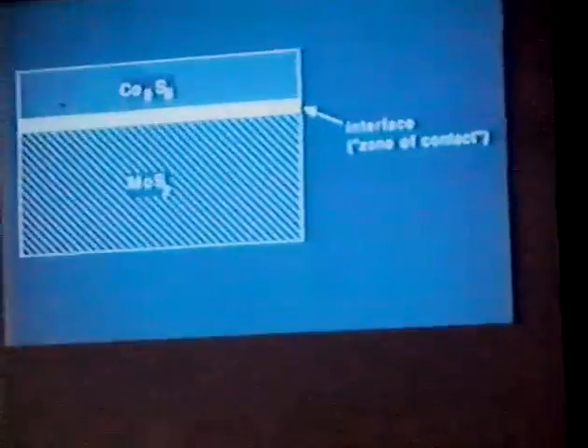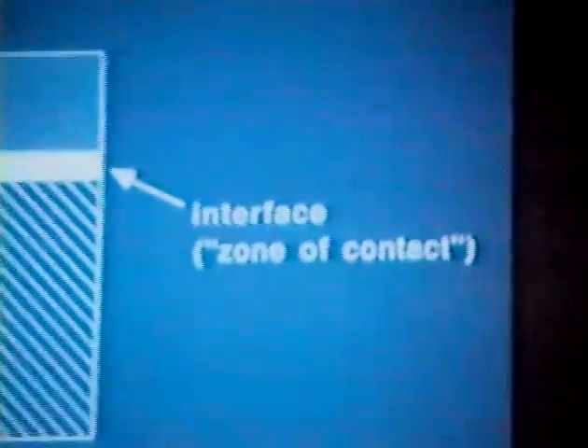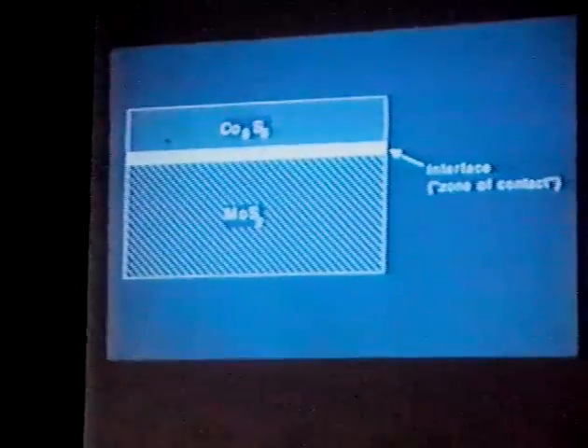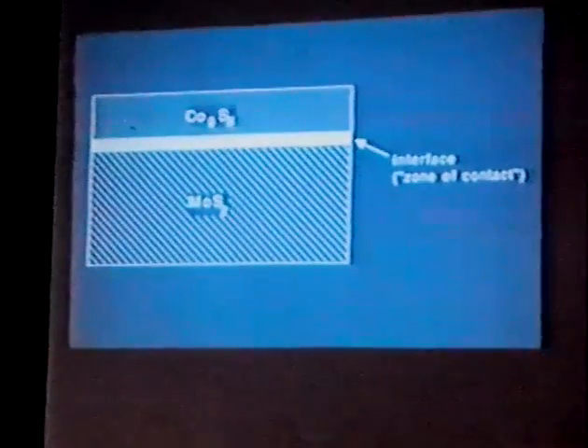So I think if you read the literature with this kind of picture in mind, you can see that a lot of the theories turn out to be really saying the same thing: at high loadings you'll see this extra phase, at low loadings you won't. But the really important thing is what happens either when the phase is present at the boundary where they contact—which is something Bernie Delmon would tell you, that the phases have to be in contact—or if this phase isn't present, the interface between the cobalt and the molybdenum sulfide is really what we need to focus on as the origin of the promoted effect. Because of dispersion problems and various other issues, this question is not clear in the literature right now.